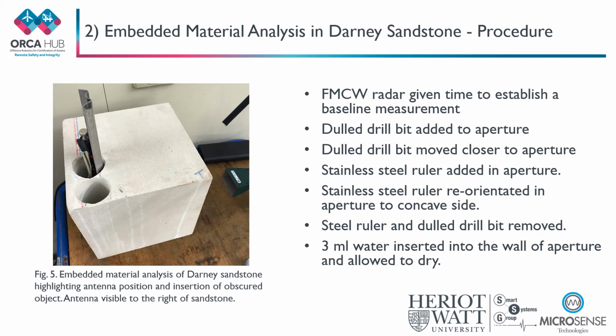Next, the stainless steel ruler was positioned inside the aperture as pictured currently. The stainless steel ruler was then repositioned so that the concave side was facing the antenna. Both stainless steel ruler and dull drill bit were then removed from the aperture to allow for 3 ml of water to be inserted onto the wall of the aperture using a dropper. This was then allowed to dry naturally at room temperature.